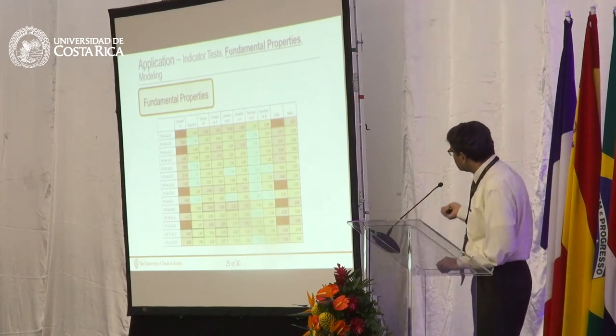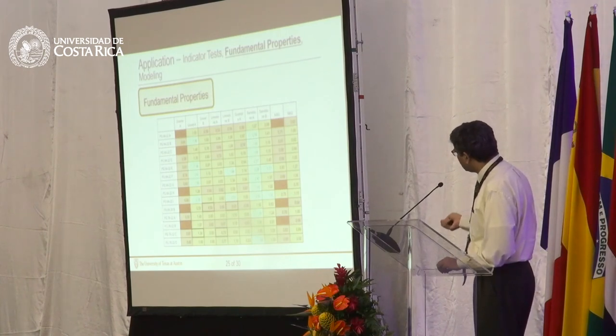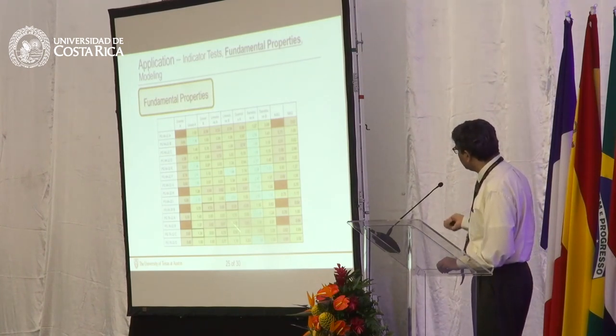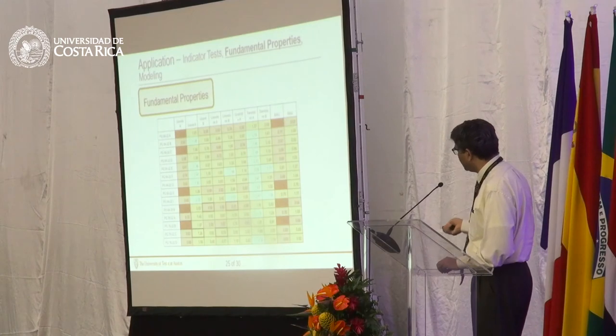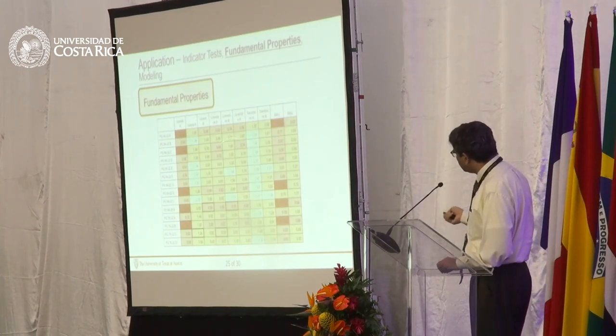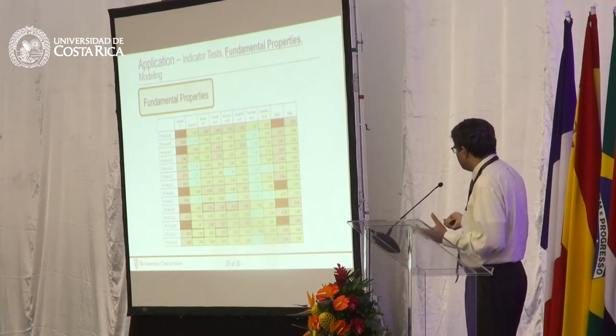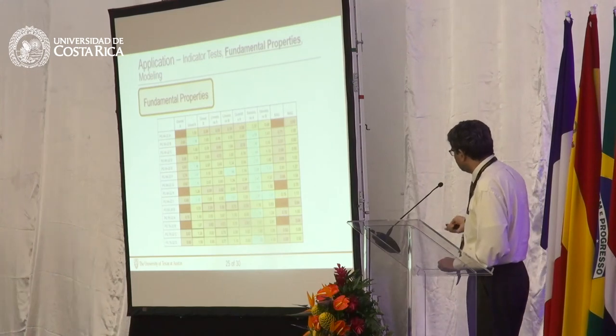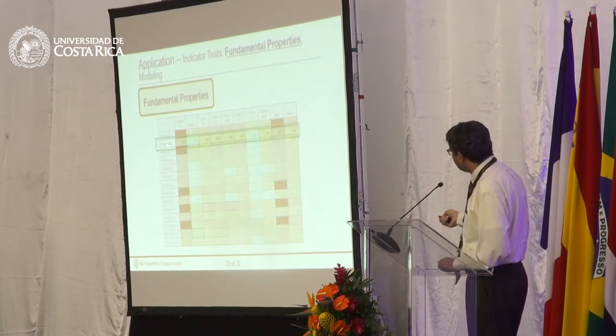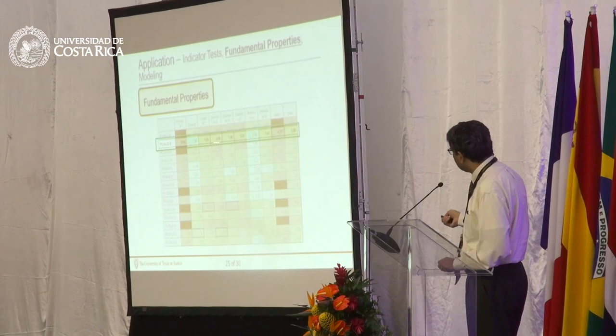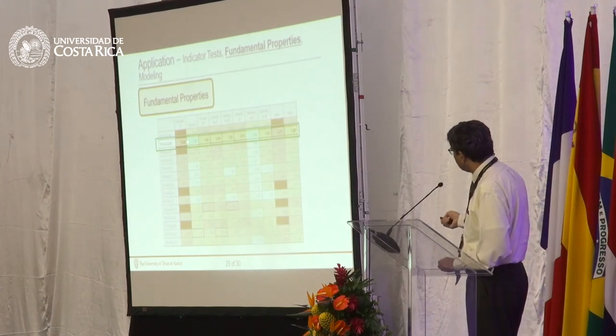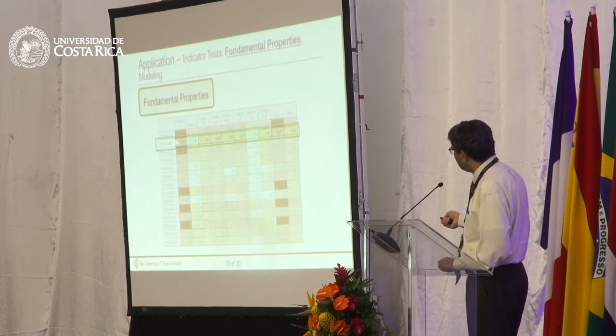What we did was we just measured surface free energy and we cataloged all the properties. This is all theoretically computed by simple measurements of aggregate and binder properties. This indexes the energy ratio. The green shows good and the orange shows bad over here. And you can see that for any given binder, depending on the aggregate type, sometimes you have a scenario that can be really bad.